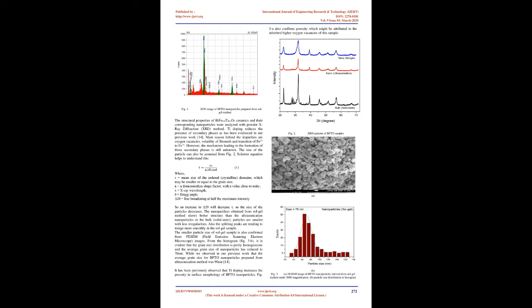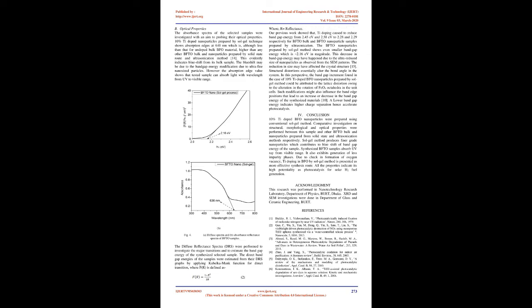λ = 1.540598 Å, in the range 2θ = 20°-80°. To study the surface morphology and chemical homogeneity of the samples, field emission scanning electron microscope with energy dispersive X-ray spectroscopy, EDS, FESEM, model JEOL JSM-7600F, was used. The UV visible absorbance spectra of the samples, range 200 to 800 nm, were recorded using a UV spectrophotometer, UV-2600, Shimadzu, where BaSO4 was used as the reference material.